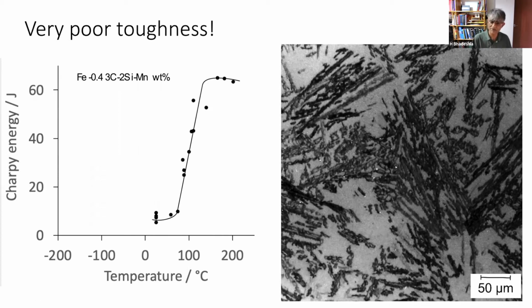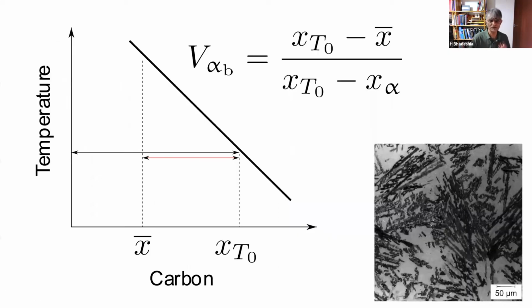It's a thermodynamic limit. Okay, let's have a look at that T0 curve again. And this is the average carbon concentration. And let's assume that the ferrite has 0 carbon. Then just by the lever rule, the amount of ferrite I can have is this distance divided by this distance. And I want to increase the amount of ferrite in order to consume those blocks of austenite. So the amount of ferrite is given by T0 minus the average concentration, and we've taken this to be 0.